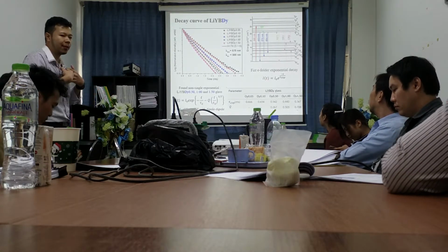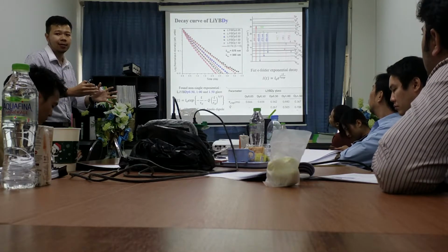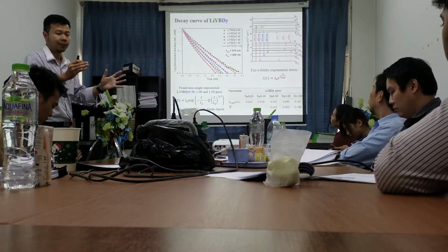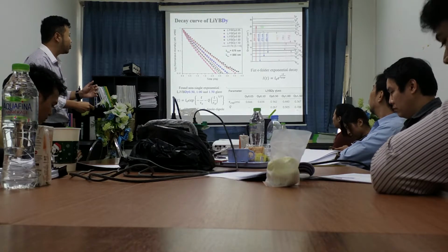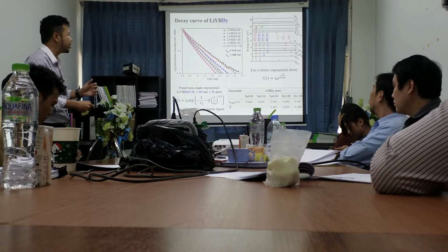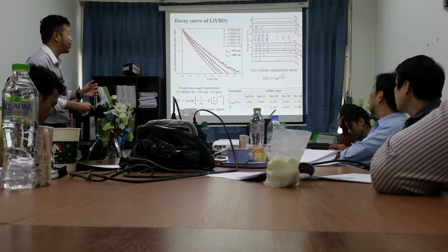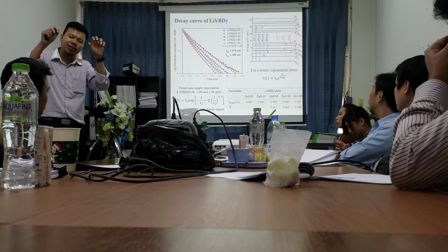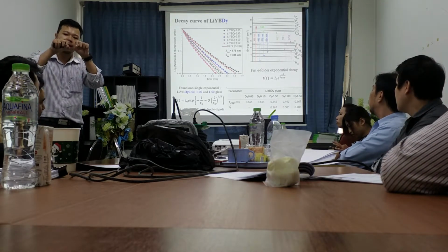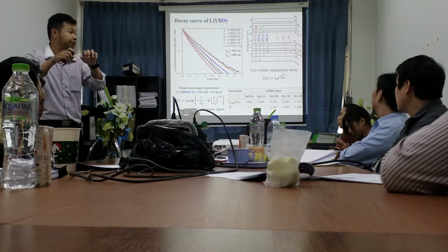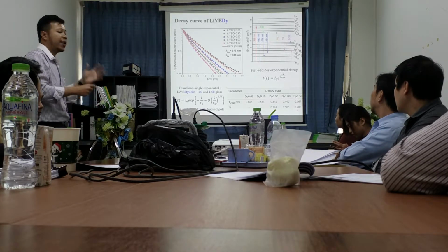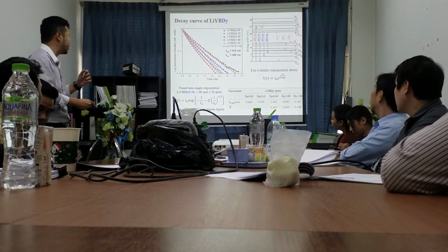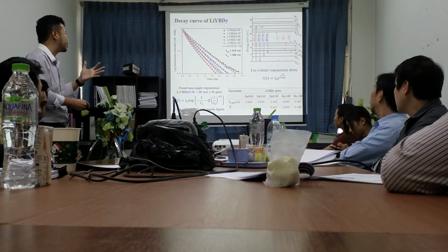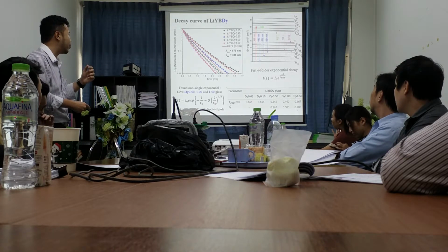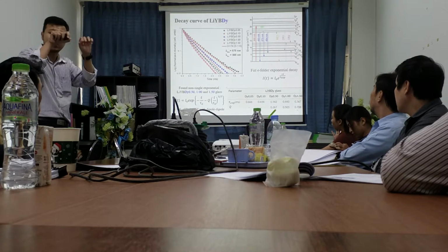The Q parameter tells us about the strength of the energy transfer. And the Q value increases with increasing dysprosium oxide concentration from 0.5 to 1.5. This means with more dysprosium ions, the ions get closer together and energy transfer is easier. For fitting, the best fit occurs when I use S equal to 6. That means the energy transfer occurs by dipole-dipole interaction between the dysprosium ions.